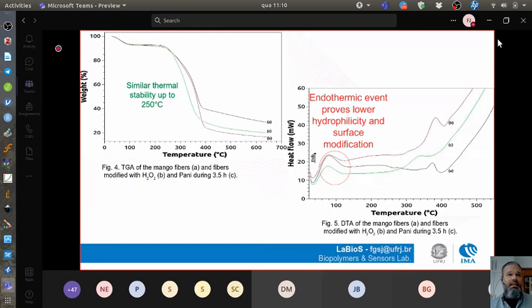Despite that, they presented similar thermal stability, with all of them being stable up to 250 Celsius degrees. And here, in the beginning of these TGA curves, we can see a loss of weight related with water.